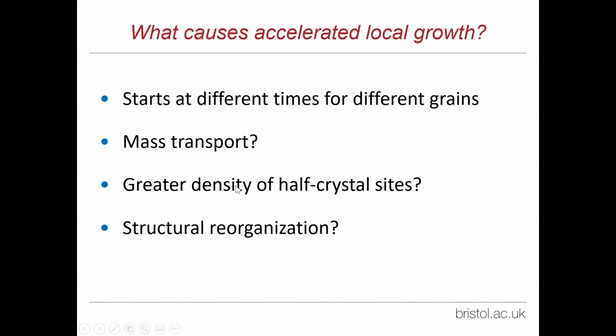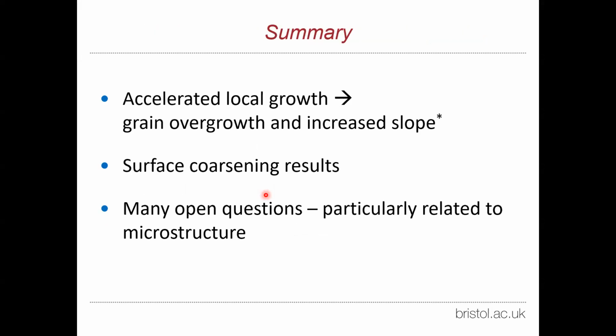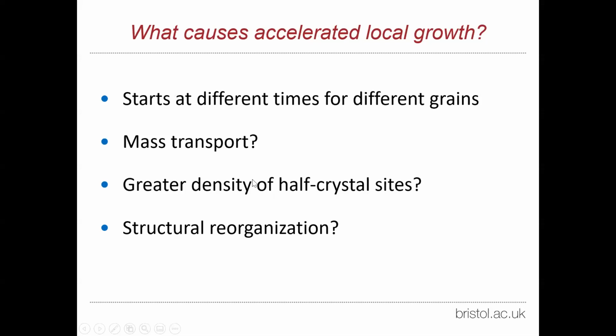What seems more likely is that it is related to the local microstructure, that there is a greater density of half-crystal sites. Half-crystal sites are key to growth of any polycrystalline metal or single crystal metal. They are sites where only half of the bonds are actually supplied, and it is those sites that are in equilibrium with whatever is being the supply of reactants, for example, in electric deposition. So one more possibility is that the surface reorganizes structurally, that what happens is that you can get twin structures, and twin structures have also got high energy sites where growth can take place rapidly.